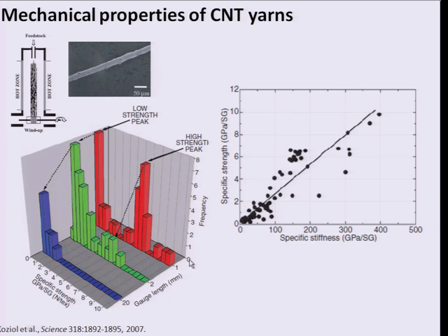And these yarns are not perfectly straight. The nanotubes are twisted and somewhat tortuous. So that is another thing that would need to be improved. So in the case of mechanical properties, these yarns over very, very small fibers are maybe a bit better than carbon fiber now, but still way worse than individual nanotubes. But if we consider the bulk characteristics of these fibers, carbon fibers that are more continuous over long distances are still better than nanotube assemblies.